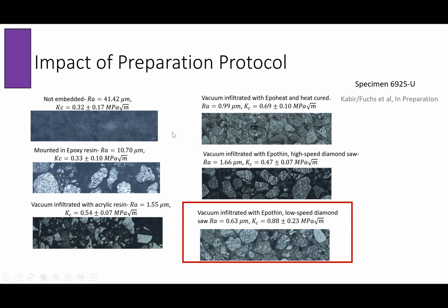And what we are showing is actually an optical microscopy picture of the top surface after the preparation process. You can see that at the beginning, we're really not polishing, we are just creating craters on the surface. And then we have different levels of more or less successful polishing, but you still have this issue of pitting and surface scratches. And then the final protocol is where we remove the issue of pitting and scratches.